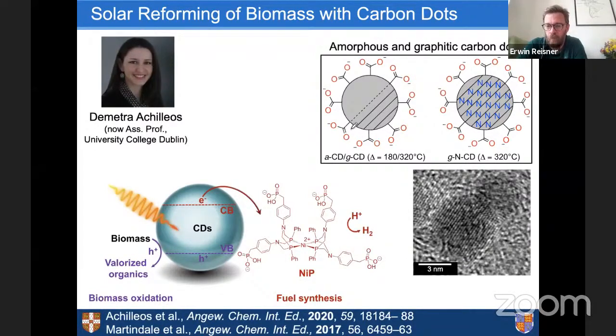So citric acid would be one example, or aspartic acid if you want to dope them with nitrogen. But you can also make them by just pyrolysis of cellulose. So in this case, using biomass to make these nanodots that we then use to photoreform the biomass. You can really see how sustainable this chemistry becomes. And depending on the pyrolysis temperature, they can either be amorphous if you use a lower temperature of maybe 180 degrees, and if you go higher, they really become nicely graphitic,